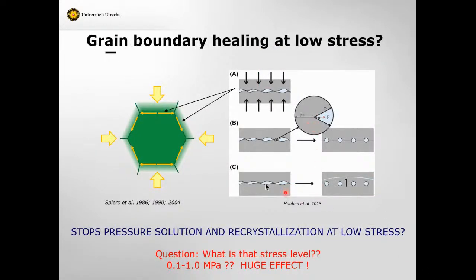If you go to low enough stress, these fluid films start doing weird things because they start actually breaking up due to the effects of surface energy. Surface tension becomes strong enough compared with low stresses to break up the fluid films. It stops pressure solution. It stops this recrystallization process.